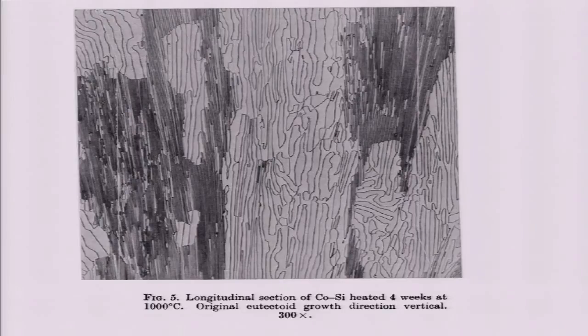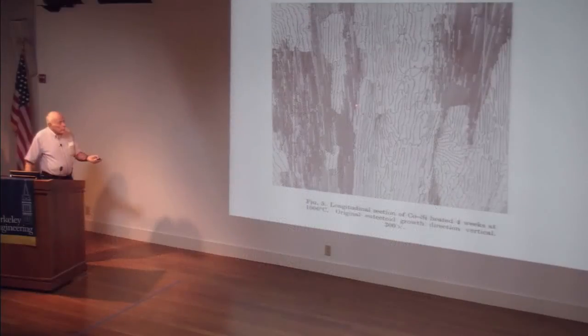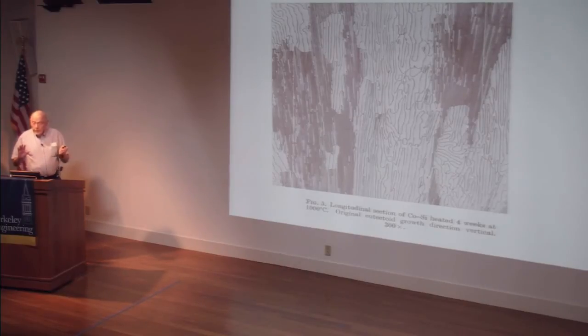This is the fine structure here, a very fine lamellar structure, which we made by directional cooling. And we were going to make a beautiful lamellar structure which had wonderful mechanical properties, but unfortunately it discontinuously coarsened. Now what's happening here is that it's not moving in this direction very much. It's running in this direction, and it's not going out in this direction. Now, if I convert this to that, I have the same free energy change as if I convert this to that. So there should be no difference in free energy change no matter where the boundary moves.